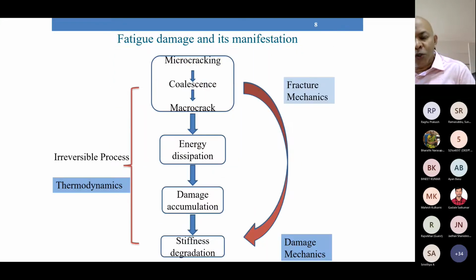When subjected to fatigue loading, we have micro cracking taking place in the concrete. These micro cracks coalesce and form a macro crack, due to which a lot of energy gets dissipated. This energy dissipation is an irreversible process, so the irreversible laws of thermodynamics can be applied, and the damage keeps getting accumulated with an increasing number of cycles, which leads to stiffness degradation. To explain this complete mechanism, we can use the principles of fracture mechanics or damage mechanics. In this work, we have used both these principles, and we have also interlinked them through energy equivalence, which I will be presenting.